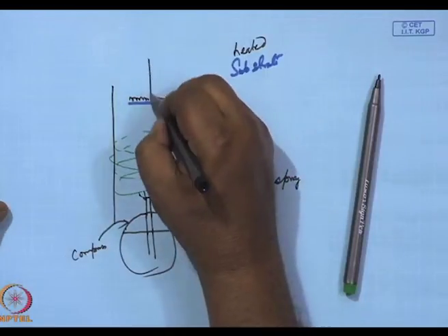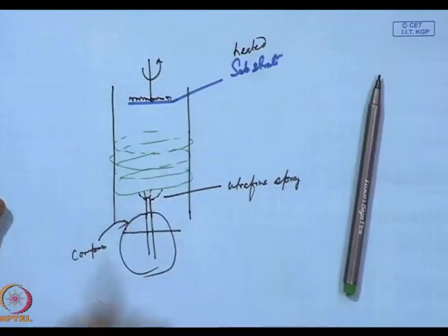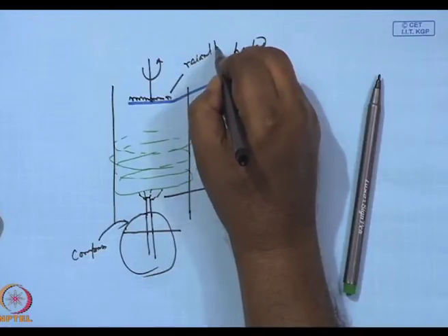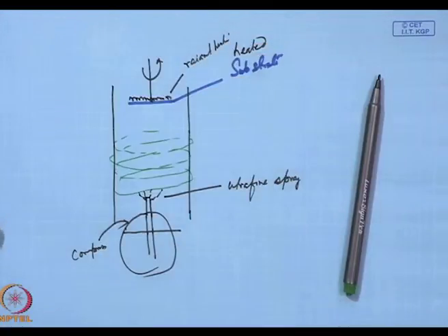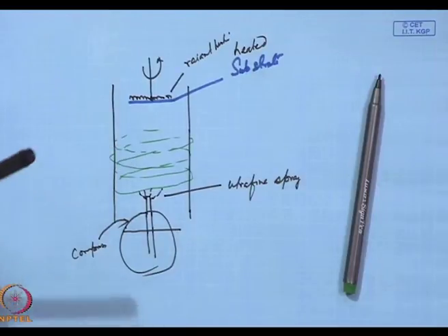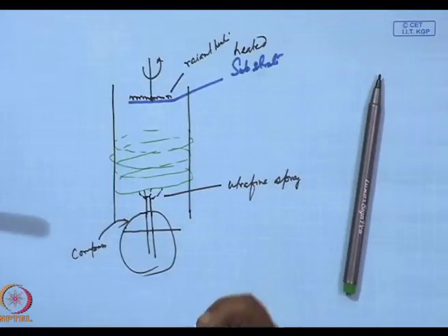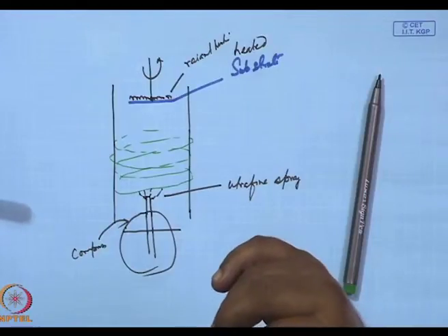Of course, the substrate is rotated. This is a radiant heater behind the substrate. So, now I have got a heated substrate. I am using the nebulizer to spray zinc acetate through this tube into a hot zone, and after it passes through the hot zone, it is purely zinc oxide.